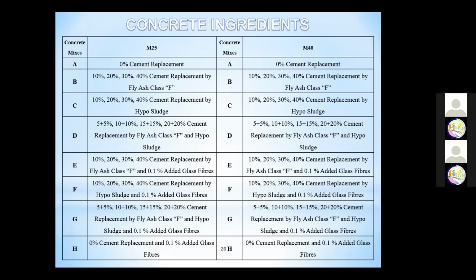Then E is the addition of glass fiber 0.1% in fly ash. F is the addition of glass fiber 0.1% in hypo sludge concrete, with the cement replacement with the hypo sludge. And G is also 5+5%, 10+10%, 15+15%, 20+20% replacement of the fly ash and hypo sludge with the cement and the addition of 0.1% glass fiber. And H is the 0% cement replacement and 0.1% added glass fiber.